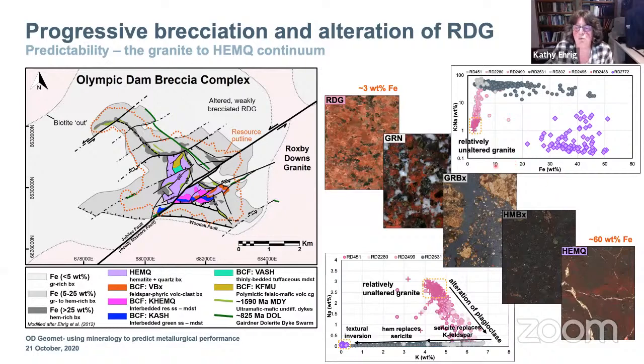If we plot the simple weight percent of iron in the rock versus the sodium-potassium ratio, we start off in fresh Roxby Downs granite, and we're really going to look more at the edges of the deposit. So we go out in real fresh Roxby Downs granite, and we can start seeing a progressive transition. We turn over as we hit the edges of the deposit, and we just start adding iron in. And this is just an example of what the HEMQ, or that more center part of the deposit, looks like. And why I like these images, or any images, when we're doing predictive modeling, is we like lines and we like curves. And as soon as we see that, we can start doing something with that.